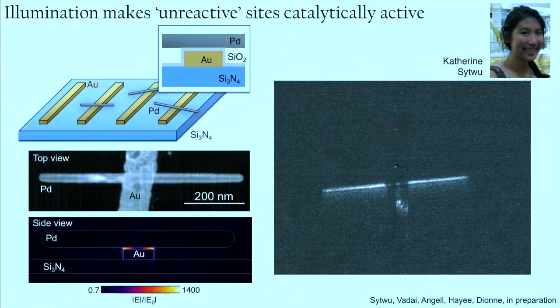what we really wanted to do is make more of the catalyst area active. And these measurements kind of pointed to a design principle, which is namely that we want to have an electromagnetic hotspot that spans almost the entire catalyst area. So as a proof of concept, we designed this catalyst structure where we have a gold nanobar, and then we put just about 2 or 3 nanometers of silicon dioxide on top of it, and then we put our palladium nanorods on top.